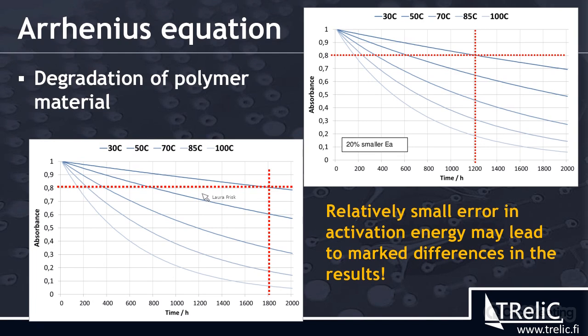So here's just a quick example. This is a degradation of polymer materials in which Arrhenius worked really nicely. There was some error in our activation energy. So here you can see that a 20% change in the activation energy actually decreased the time by 600 hours, so one third of the original. So the risk here is typical to many models, that you have a relatively small change in some value, and it can actually end up having a relatively large change in the actual used life.